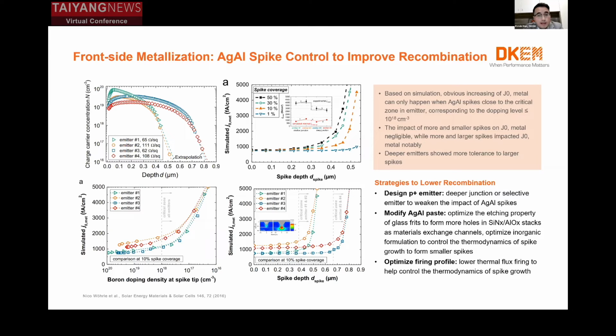So this gives us three strategies to achieve lower recombination. First, we can design a deeper junction or use a selective emitter to weaken the impact of spikes. The second one is that we can try to modify our silver aluminum paste system to achieve smaller spikes as well, because it's a thermodynamic process. So we can modify our paste inorganic system to try to control the process. The third one is that we can use lower thermal budget firing to help control the size of the spikes. With all of these efforts, we can control the size of silver aluminum spikes, then deliver good recombination.